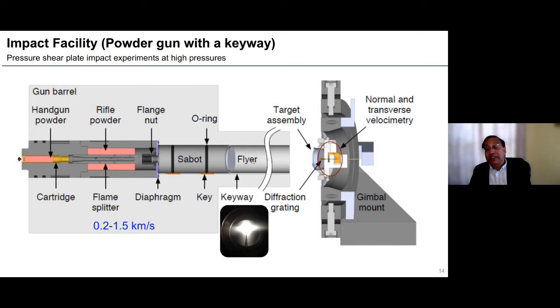When you launch these projectiles and want to impact at an oblique angle, we cannot tolerate rotations in the projectile, because then you won't have parallelism between the impact faces. So to prevent the rotation of the projectile, we introduce a keyway in the gun. With the facility we have, we can launch projectiles in the range of 200 to 1500 meters per second. Normally, in current plate impact experiments, projectiles are launched at 400 to 500 meters per second using single-stage gas guns, and this is also limited, as I mentioned, by the analysis being limited to about the Hugoniot elastic limit. So this is the first modification we made.